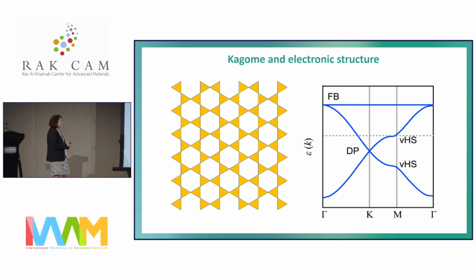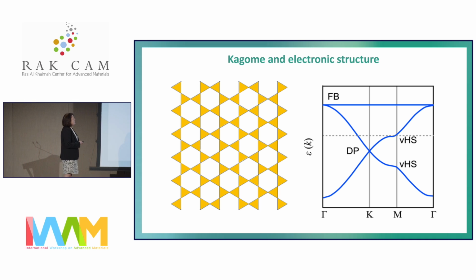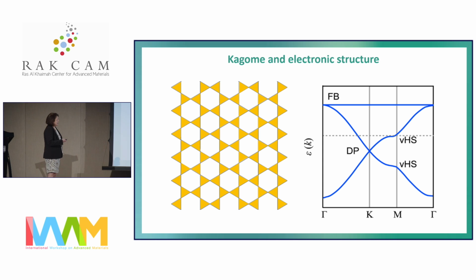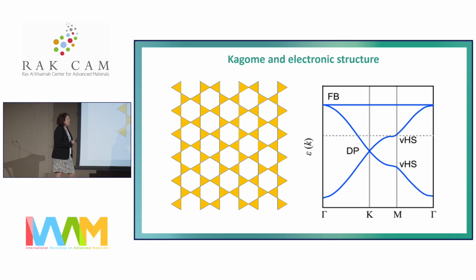because the Kagome lattice is now so popular, because if you simply make a tight binding model, for example, simply you put a hydrogen atom on this Kagome lattice and you calculate the electronic structure, it's nearly as interesting as graphene, maybe even more interesting, because the electronic structure would lead to a flat band, a Van Hove singularity, and a Dirac cone. So this is very interesting.